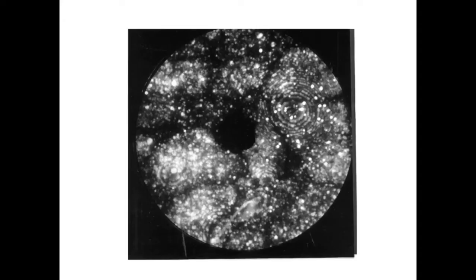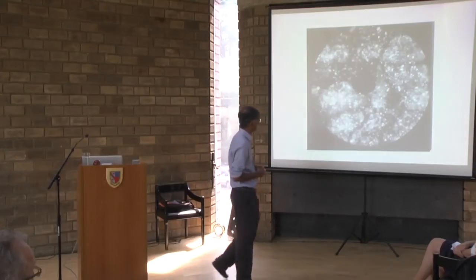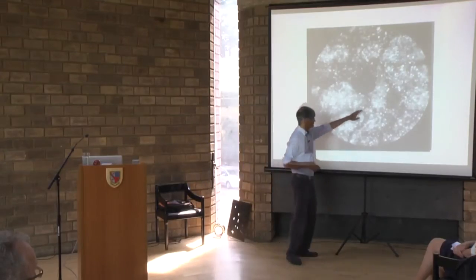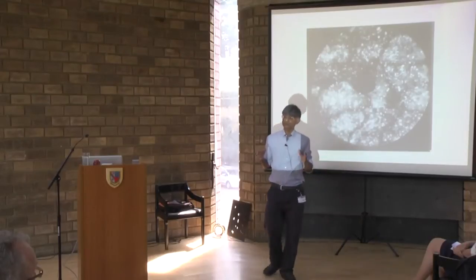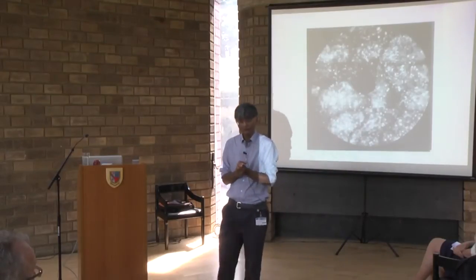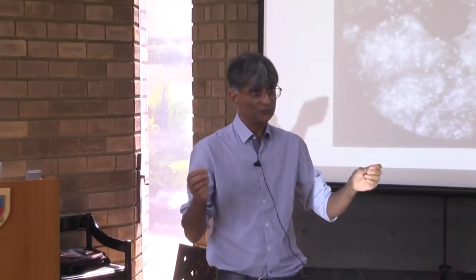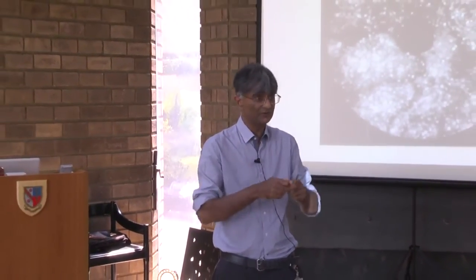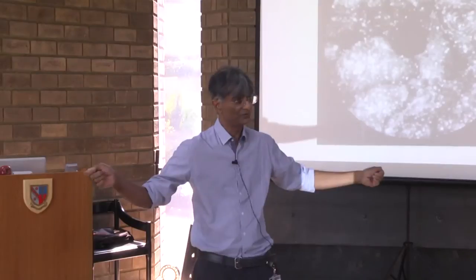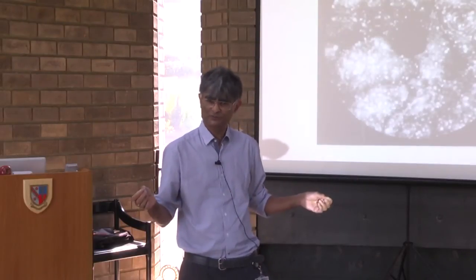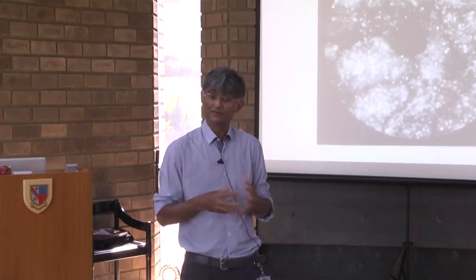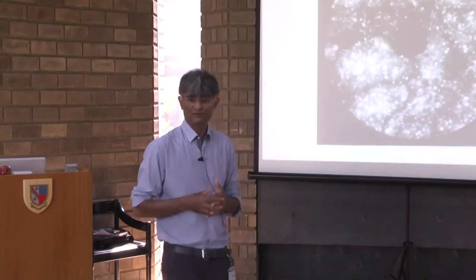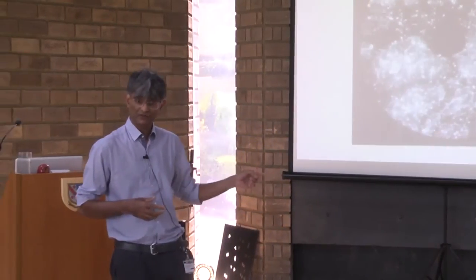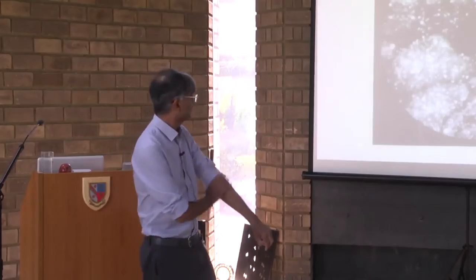So it seemed like we already had a very strong material, and the reason why it is strong is this picture shows individual atoms. We have equipment where you can see individual atoms, and each dot is a single atom. And you see these dark regions here, those are the boundaries between the crystals. So the crystals have become so fine because the material is produced by taking, let's say, 50 grams of material and stretching it out into 2 kilometers. That's a huge amount of deformation. And that introduces huge numbers of defects, and in this case, the defects strengthen the material. Okay?